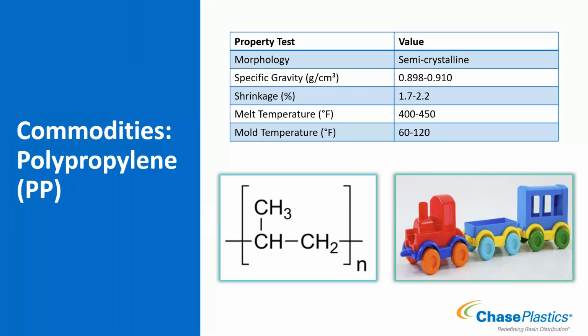But the ones that I do cover, we're going to start with polypropylene. So morphology, it is a semi-crystalline material - we covered that means you're going to have a little bit more shrinkage. The shrink for polypropylene is in the 1.7 to 2.2 range, or 17 to 22 thou range. Your specific gravity, generally unfilled, is going to be about 0.9 to 0.91. Because it's lower than 1, which we compare to water, these materials will float. If you've ever worked with a propylene part or pellets, if they're unfilled, pellets will float or parts made of it will float.